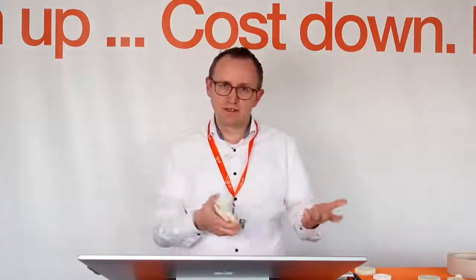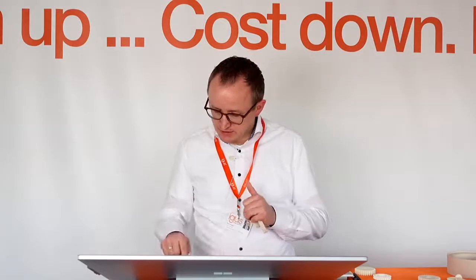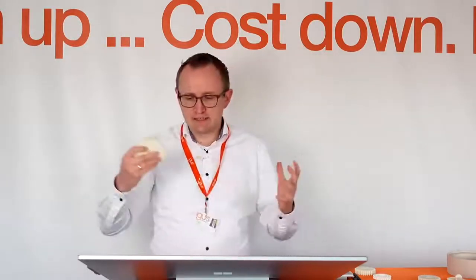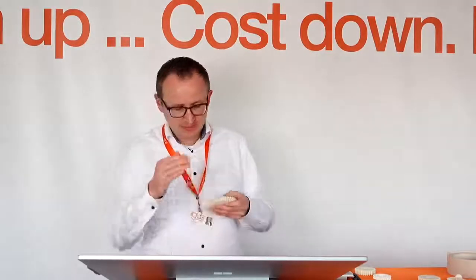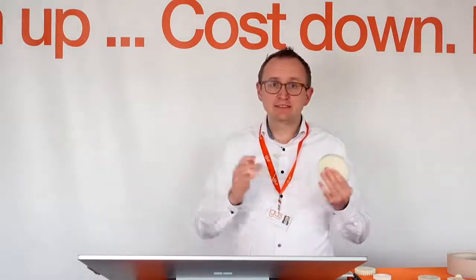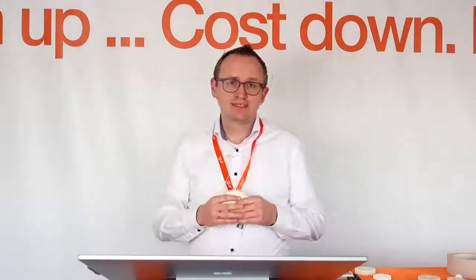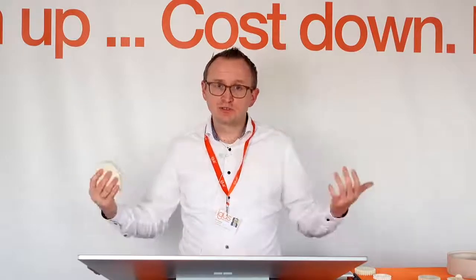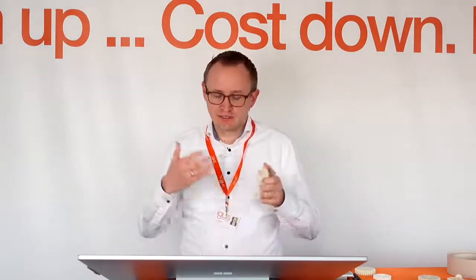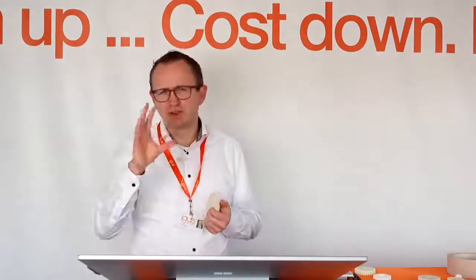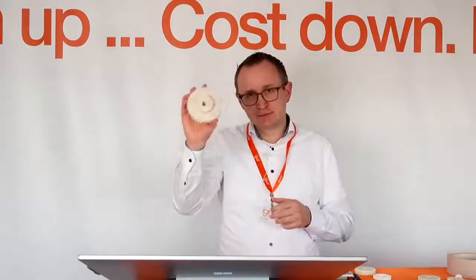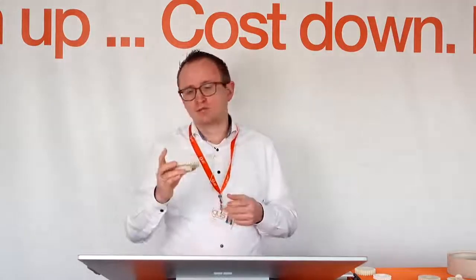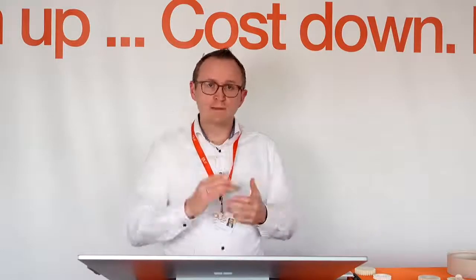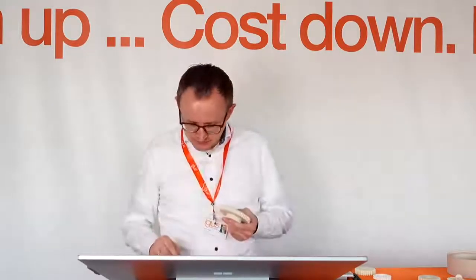With rework, we can of course achieve better tolerances. Then you need to decide if this is good enough for your application. We found out that it is good enough for lots of applications, because, as I said already, we printed around 40,000 gears last year by laser sintering, with lot sizes from 1 up to 6,000.